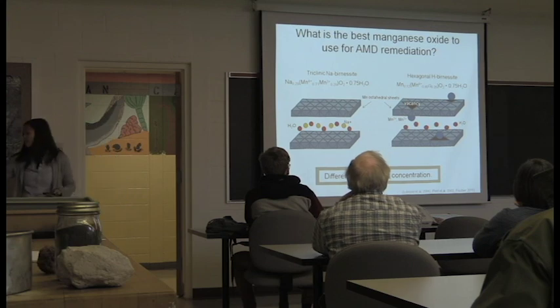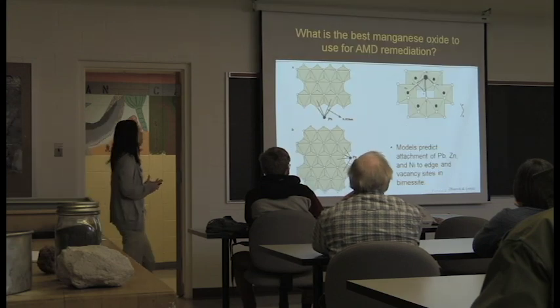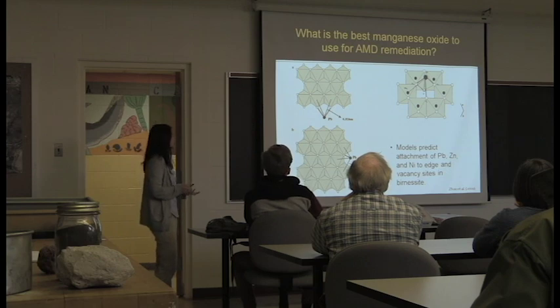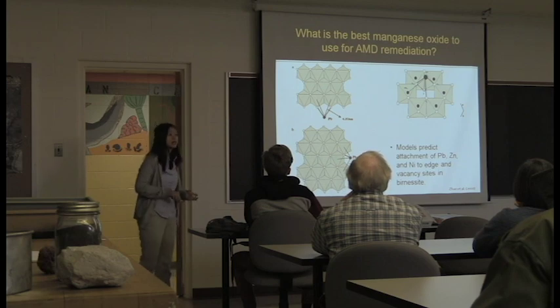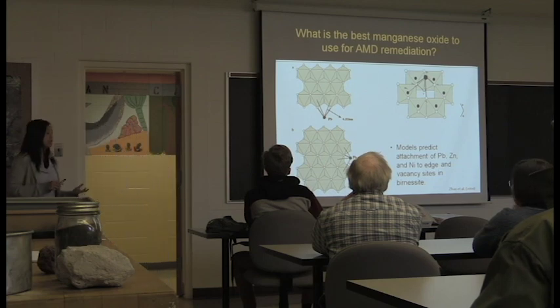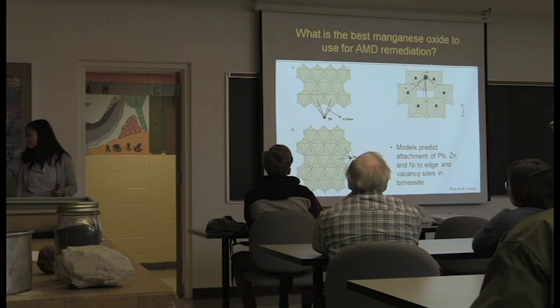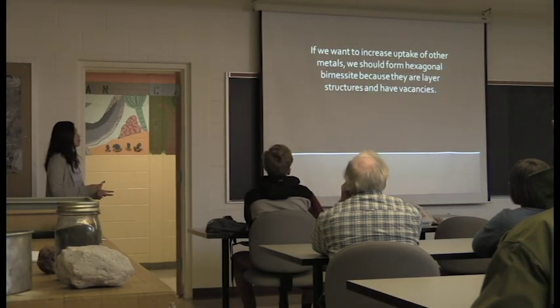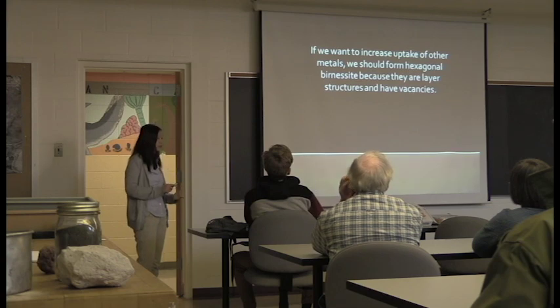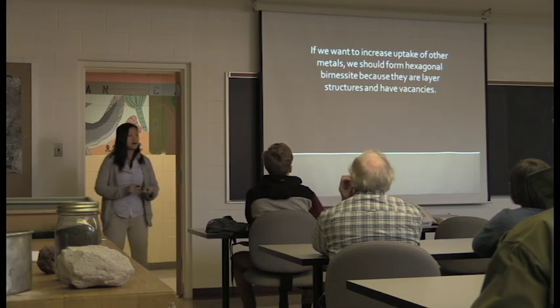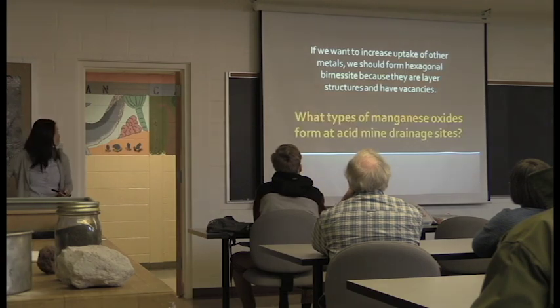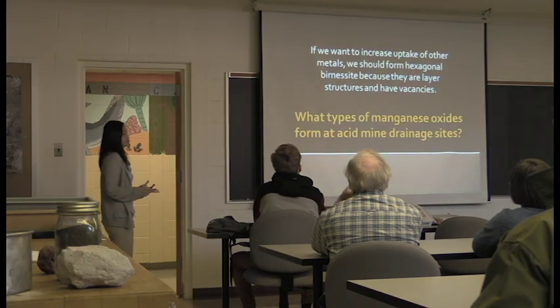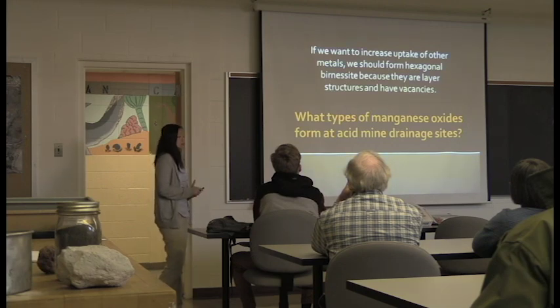The reason these are important, it turns out, is that some computer modeling has shown that a lot of different metals, such as lead, nickel, and zinc, not only attach to the surface and edge sites of your manganese octahedra, they can also attach to these holes. So if you want a lot of metal uptake, then you want a lot of these holes in your mineral. That means we want hexagonal birnessite, which is not only layered, which makes it very chemically reactive, but also has lots of these holes in its manganese octahedral sheets. But we don't really know what types of manganese oxides are found in our acid mine sites yet, so we initially have to investigate this question.